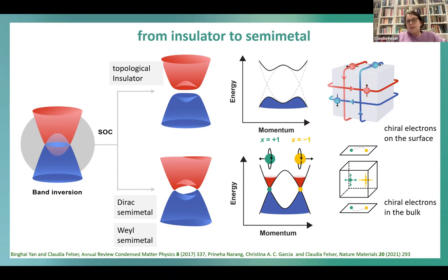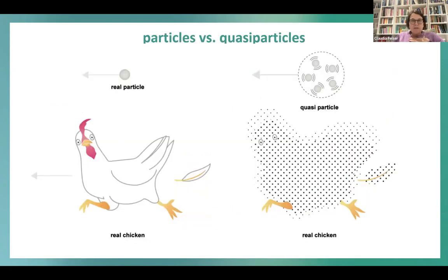And this leads to very, very interesting properties, not only that you have this very special surface state, which you see here as arcs between the yellow and the green points on the surface of the crystal, but you also have special properties in the crystal's bulk at these points. And on the next slide, we probably see more.